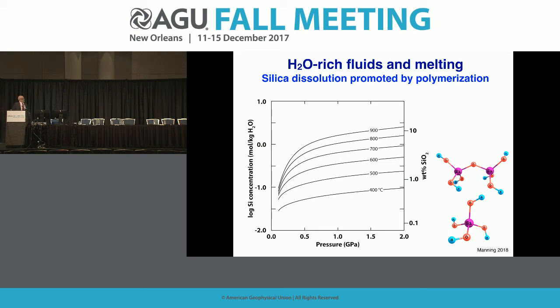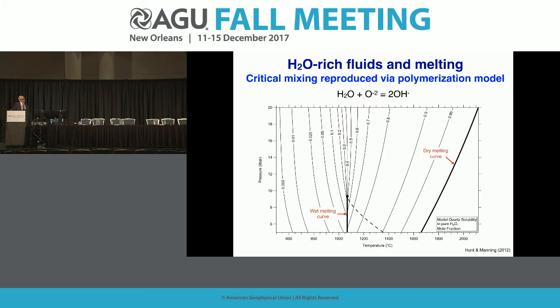And it works great for all the way up to about 800 degrees C. But at 900 degrees C, our experiments provide us with an indication that the solubility is significantly higher than the predictions based solely on the monomer and the dimer. And the reason for this is because there is additional polymerization. So now we're seeing the ingrowth at these very high temperatures of something that must be a trimer, whether a ring or a linear chain.